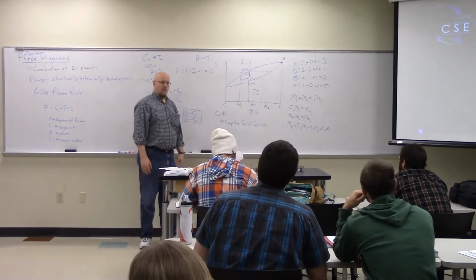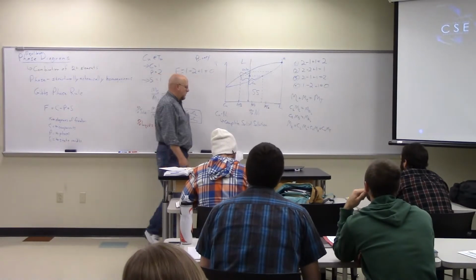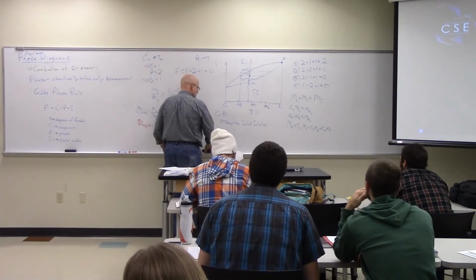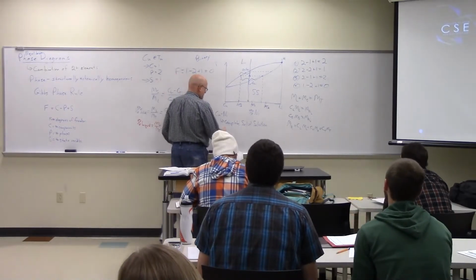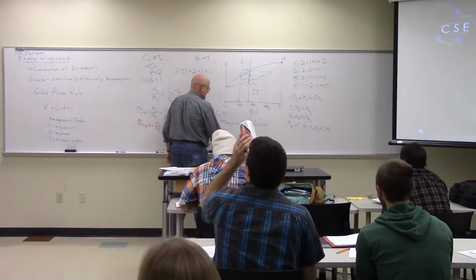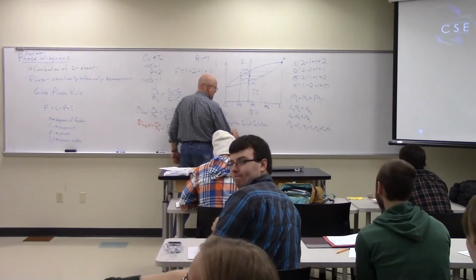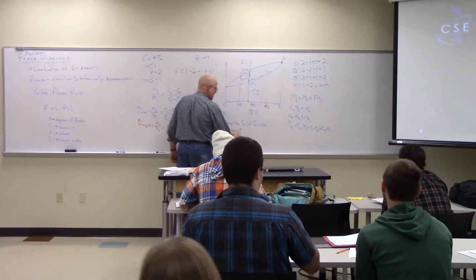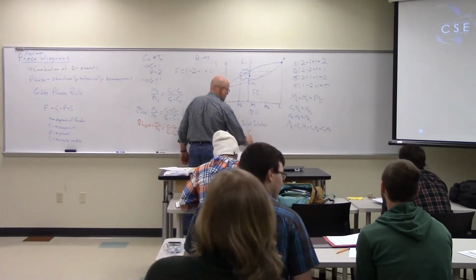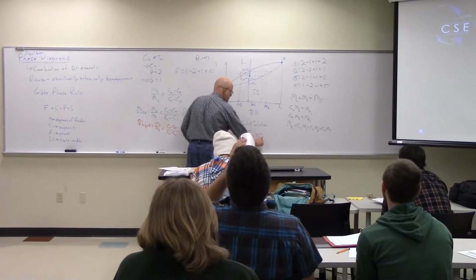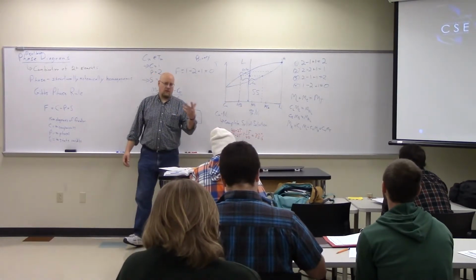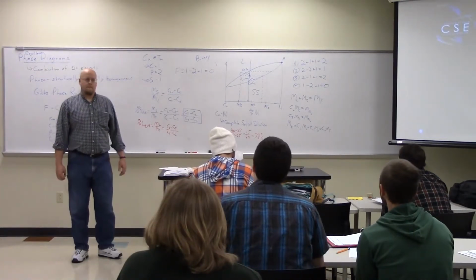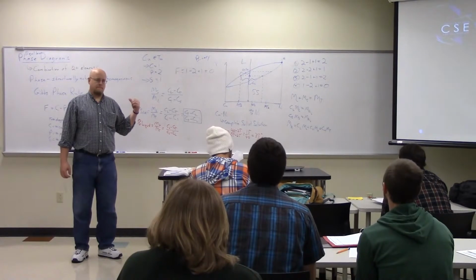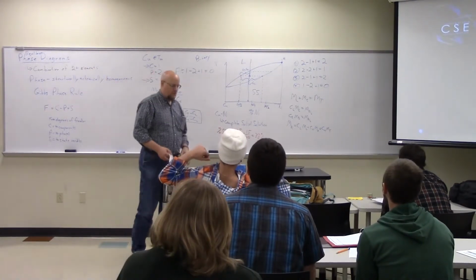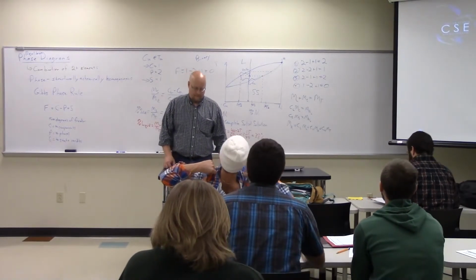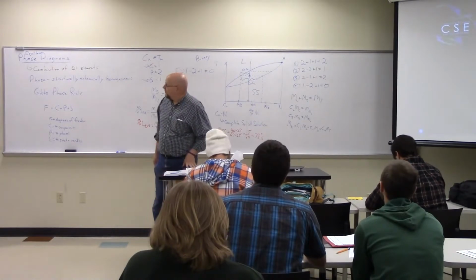My numbers are just approximate on my horizontal dimensions. It's not quite a half, really. This is probably not 45, it's probably 40. I'm going to rewrite that in a different color because Dan can't see that anyway. So the percent solid solution is now, let's make it 40 instead. 40 minus 25 over 65 minus 25, that's 15 over 40, which is 38%. So it's 38% solid and 62% liquid. Good? Okay. Does that make sense to everybody? Okay, then let me do one more phase diagram.